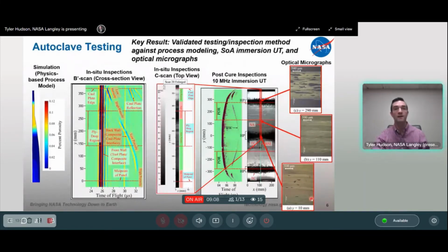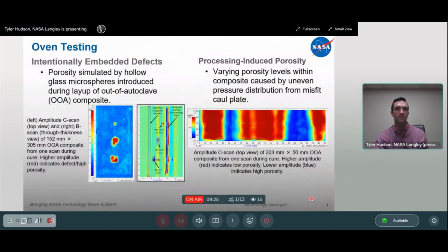And the takeaway is that we have a validated testing inspection method, and we validated it against process modeling simulations, state-of-the-art commercial ultrasound systems, as well as optical micrographs. So we're very confident in the results that we're getting.